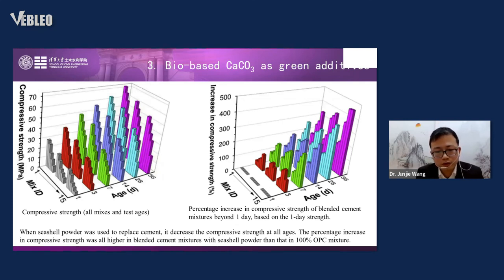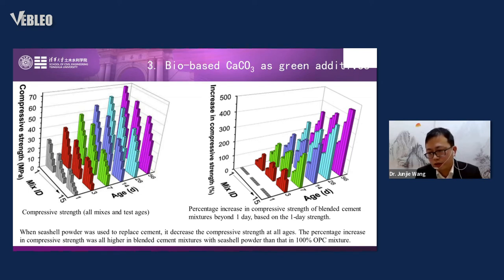Here are compressive strength results of all 15 mixes. We see it decreases with increasing seashell powder content. However, when we consider the rate of strength increase compared to the 1-day strength — at 3, 7, 14, 28, and 56 days — we can see that seashell powder actually increases the rate of strength gain over time.